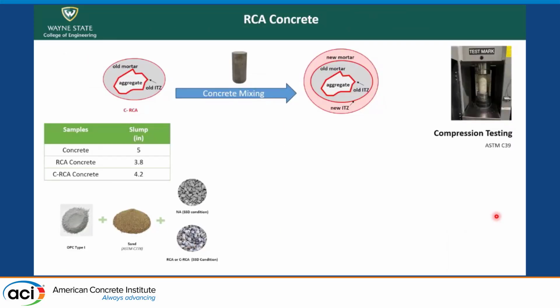Now we wanted to see what results we get when we include the RCAs into concrete. So having the carbonated RCAs, we introduced them into this new cement mortar mix and created a new concrete mix. So now we have a new mortar which is attached to the RCAs and a new ITZ. And we examined 3 different samples: concrete with natural aggregates, concrete with RCAs that were not carbonated, and concrete with the carbonated RCAs.